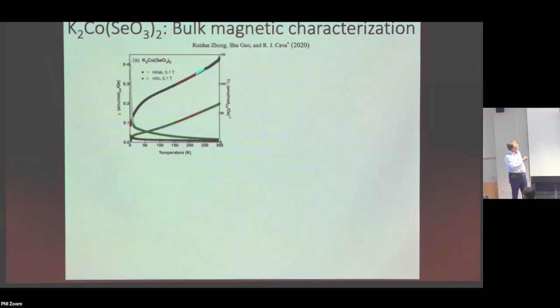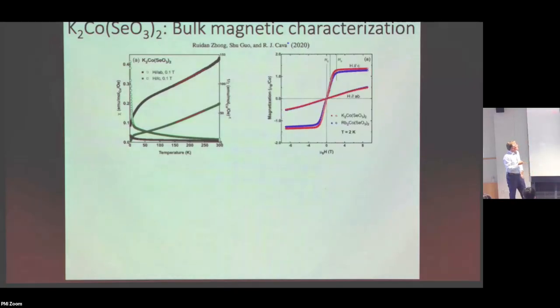Actually, by looking at the inverse susceptibility versus temperature, we can get a measure of the strength of the interactions in the system from the Weiss temperature, and that will allow me to choose which instrument I should use. We've got many different instruments. I choose the one that's good for this energy scale, essentially.